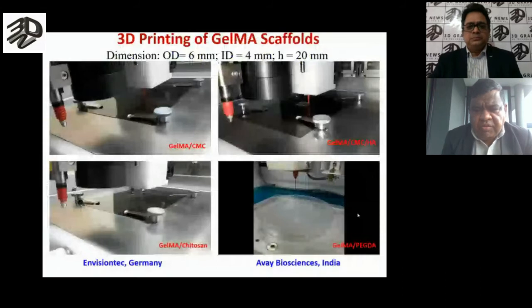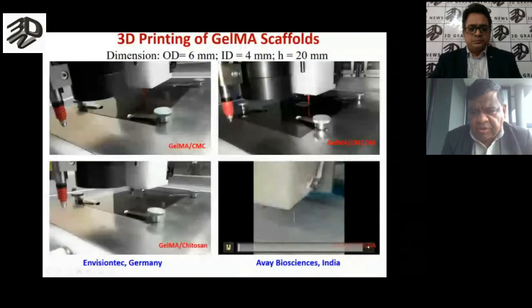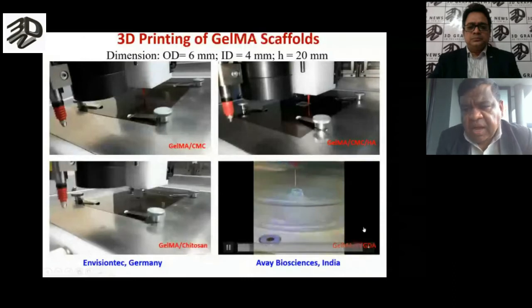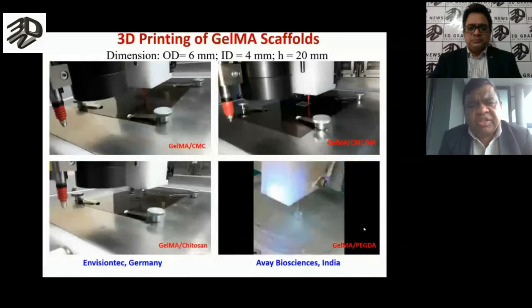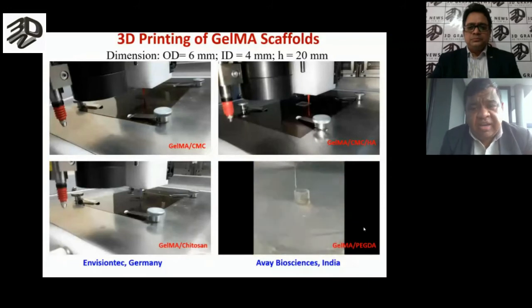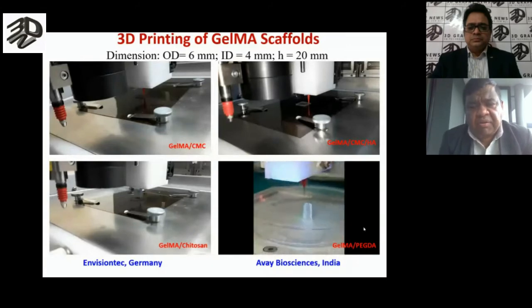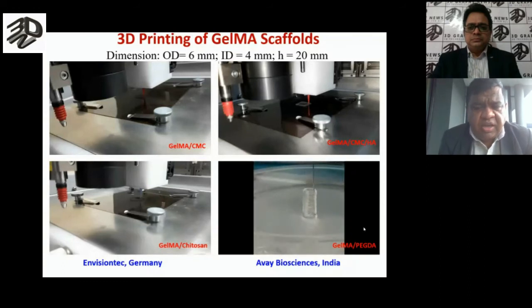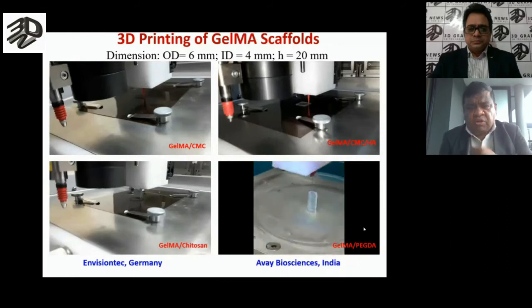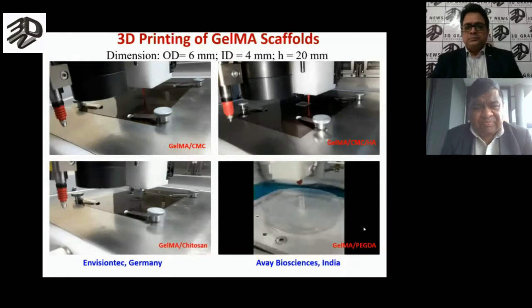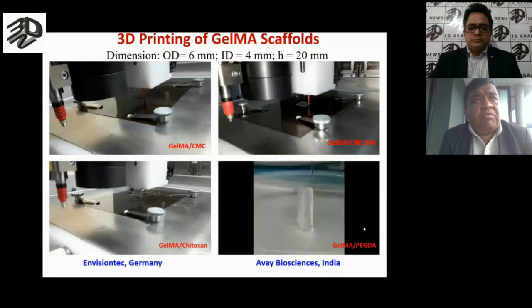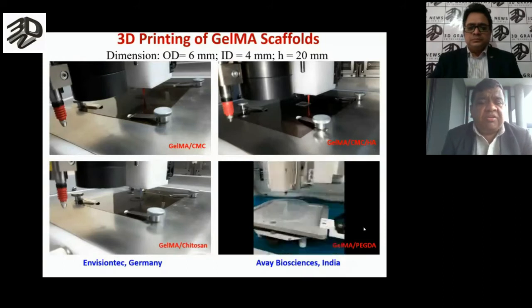Okay, so this is the same Avay Biosciences 3D printer we have used to print our nerve grafts. Now I'm showing you how this structure is getting built. Typically neurosurgeons require a 20 millimeter long graft with around 4 millimeter internal diameter and a wall thickness of 2 millimeter. So we are able to fabricate this kind of nerve graft by in situ UV cross-linking. In 3D printing, two things are important: one is the printability, another is the buildability.